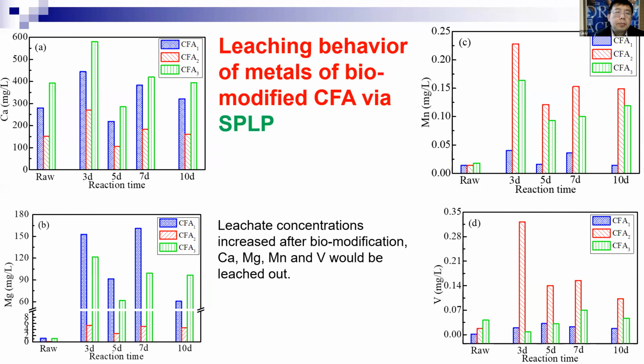It's because they have calcium carbonate that can precipitate. It seems like it doesn't contribute too much to reducing the leaching of calcium ions. So that may be related to bioleaching of bacteria. But when we look at the magnesium, we see that the leaching concentration is much higher after 3 days compared to the raw fly ash. So it seems more metal leaching out for manganese, and also the same thing for vanadium,